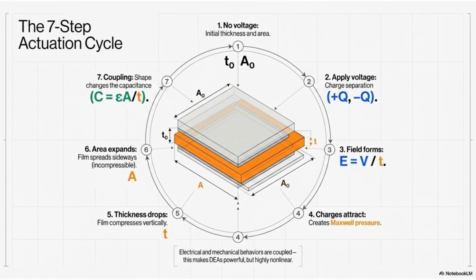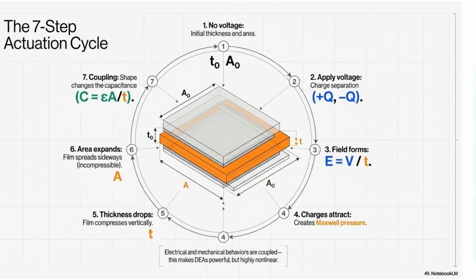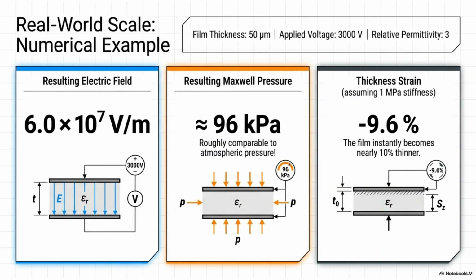The 7-step actuation cycle starts with no voltage, followed by applying voltage, which forms a field. Charges attract, creating Maxwell pressure, which drops thickness. Area expands, and coupling changes capacitance, completing the cycle. A numerical example with a 50 micrometer film and 3000 V applied voltage results in a strong electric field, Maxwell pressure comparable to atmospheric pressure, and nearly a 10% reduction in film thickness.